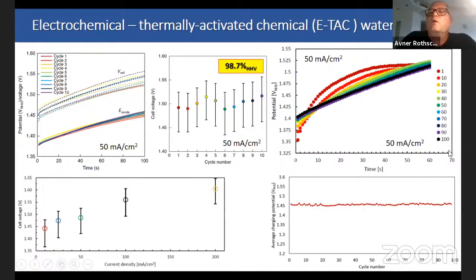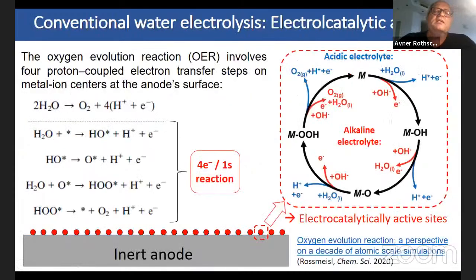So here you see 100 cycles, except for the first 10 cycles where the state of charge of the electrode changes. Once it reaches the operation range, then all the remaining charging curves repeat themselves exactly. And if you look here, for 100 cycles, the average potential stays exactly the same. We can also increase the current density with a small payment in the operation voltage. The reason why this reaction is so efficient is explained here.